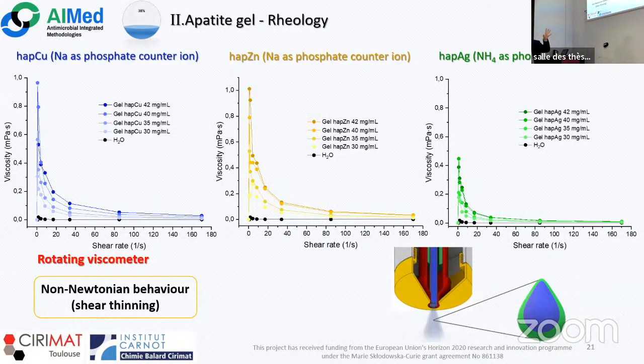On the other hand, for the silver case, the values were almost half compared to the ones that we see for the others. That can be due to the counter ion and to the higher crystallinity, because the higher the crystallinity, the lower the surface reaction.